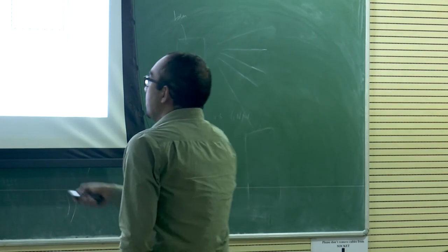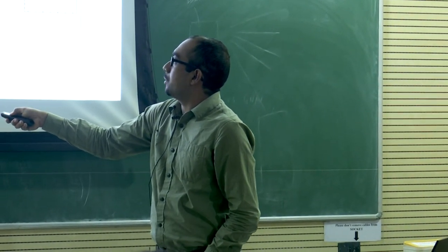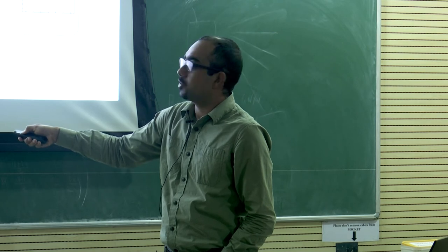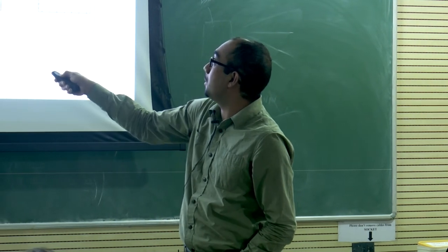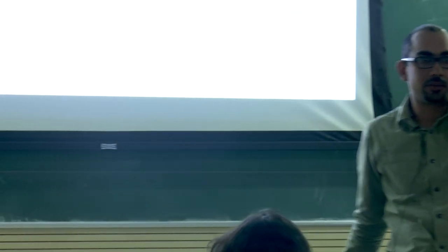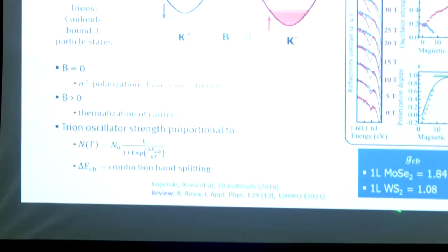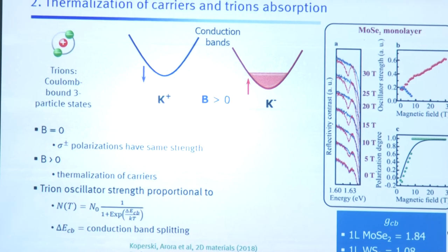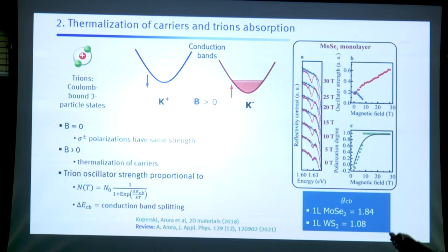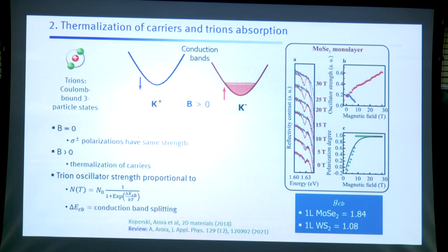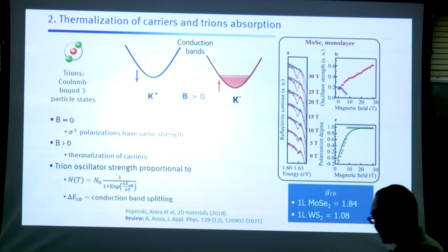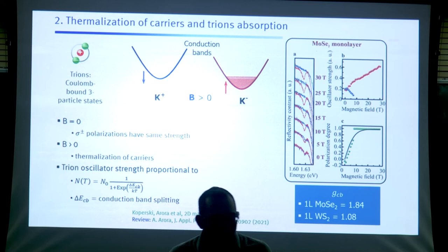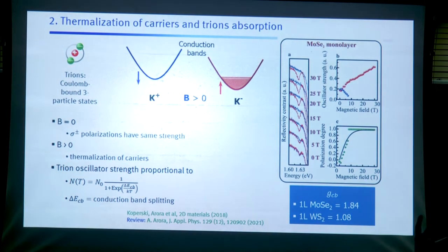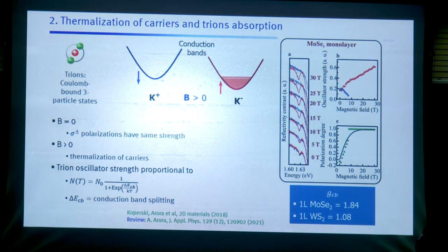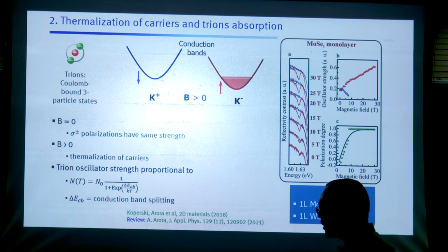That also follows this. The trion oscillator strength I am talking about here follows a Fermi-Dirac distribution function, where there is this delta E_CB, which is the Zeeman splitting of these two valleys. This Zeeman splitting can be found, and we found the g-factors of the conduction bands directly. The message here is that we can tune the population. If you want to make valleytronic gates or valleytronic devices, you need to do two things. You have to control the phase between the valleys, and you have to control the population difference between the two valleys. This is the control of population difference, just using magnetic fields.